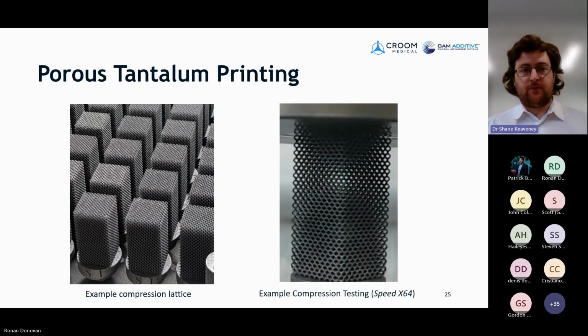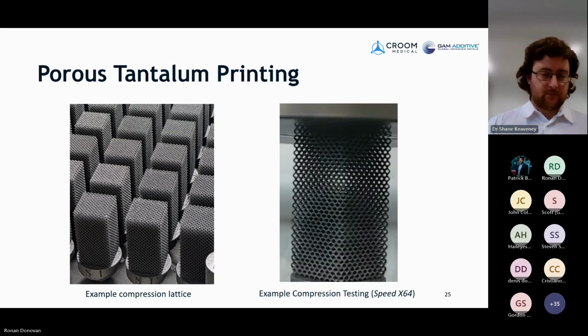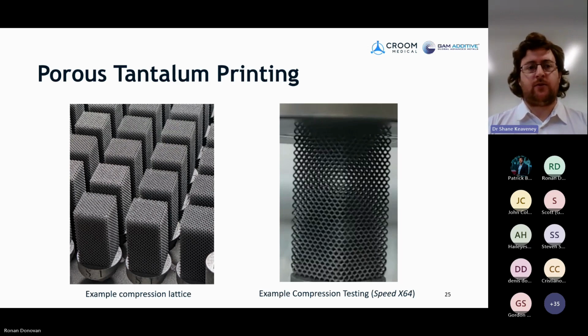In terms of the results we've seen, highly consistent. We're able to go from strut diameters of maybe 200 microns or a little bit less up to 400 microns, and of course beyond there as well. So very consistent. Easy for powder cleaning on these structures too, which is one of the points I guess we haven't touched on much here, is the density of the tantalum. So it's around 16 grams per, I forget the exact units there, but it's about 4 times that of titanium 6-4.